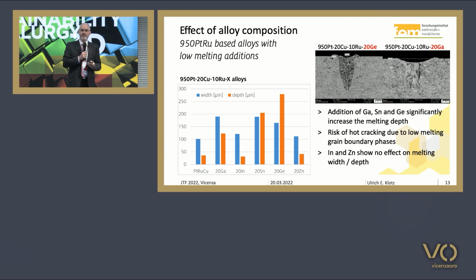We heard about the age-hardenable alloys in the presentation of Chris Corti that contain gallium, so I suppose that they might be critical in the processing with the laser powder bed fusion or SLM process, because they lead to so-called segregation. Certain elements concentrate in the liquid phase and strongly reduce the liquidus temperature, so a liquid phase remains and results in cracking if the cooling is continued.